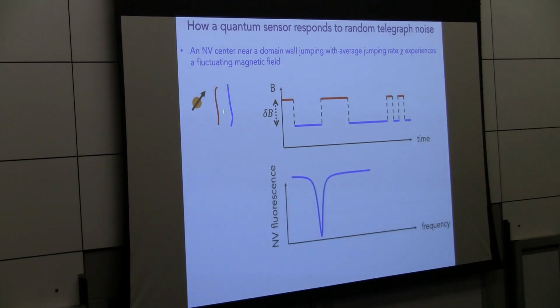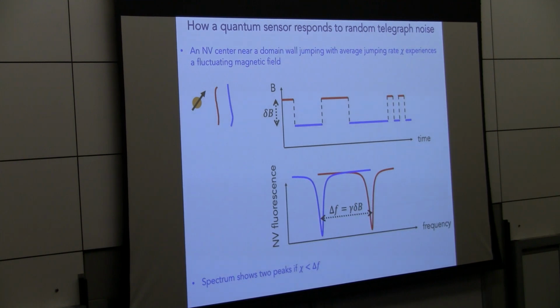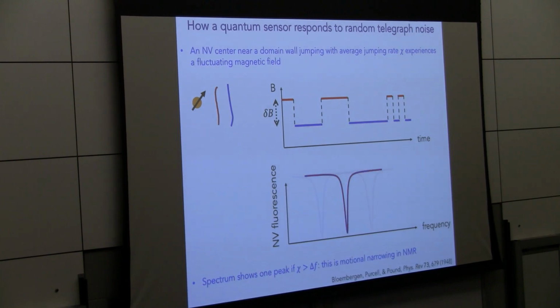Again, this is jumping, exhibiting telegraph noise with an average rate chi. So when the domain wall is in this location, the NV ODMR spectrum should look like this, where this corresponds to the magnetic field produced at the NV when the domain wall is there. And when the domain wall moves, my ODMR spectrum will move. This is what I expect to see, but only if that jumping rate, chi, is slower than the splitting between these two. If the jumping rate is faster than that splitting, you expect to see just one dip, because effectively you're seeing an average of the environment.